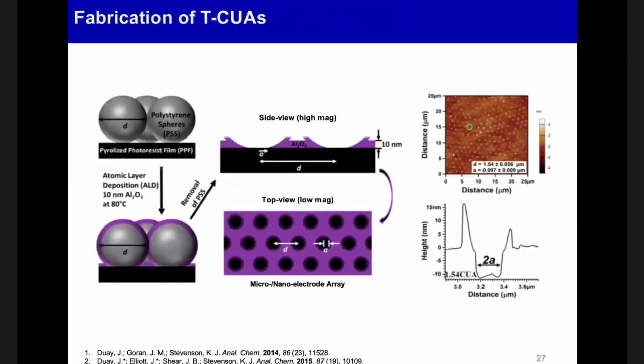So here's how to fabricate them. We start with a quartz slide, and then we apply photoresist, and then we pyrolyze it. Then we drop cast a solution of polystyrene spheres and methanol. They organize themselves into this hexagonal organization as the solvent evaporates. They stick to each other. After that, we do atomic layer deposition to apply 10 nanometers of aluminum oxide, and we do this at 80 degrees, because if we go higher, we actually melt the polystyrene spheres. Upon that, we then do various sonication baths to remove the polystyrene spheres.